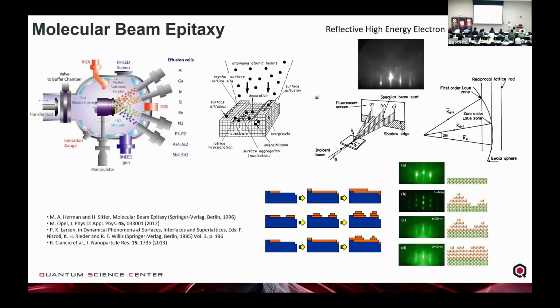And so here, the basic idea is we have these atomic sources. We put them in the vacuum chamber. We heat up these atomic sources, and the materials start to effuse from these diffusion cells. And now we'll have a crystalline substrate, which acts as a template that has the symmetry that we want our material to have. And so all of these materials will then impinge on this surface, and they'll hit the surface and rattle around. Some of them desorb, some of them move around, but then they'll start to chemically react with each other. And so this is how we form the chemical bonds, and this is how we can form new materials layer by layer. And now we can start customizing the materials that we want.